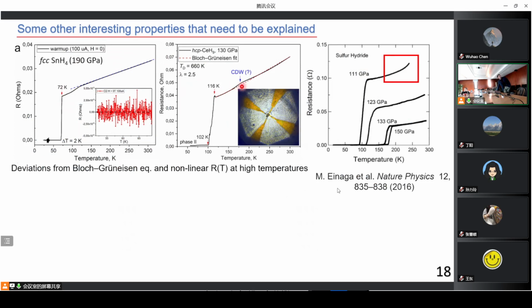A similar phenomenon was observed for cerium hydrides. We see here there is some wave, some hill on the resistance. This hill again cannot be explained within the Bloch-Grüneisen equation or the classical models. In another publication, in Nature Physics, Einaga and colleagues in 2016 published several curves for sulfur hydride. Again, we see abnormal behavior of resistance at high temperatures.